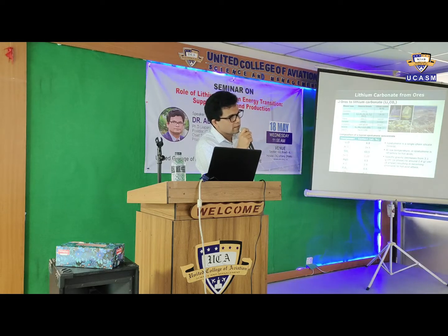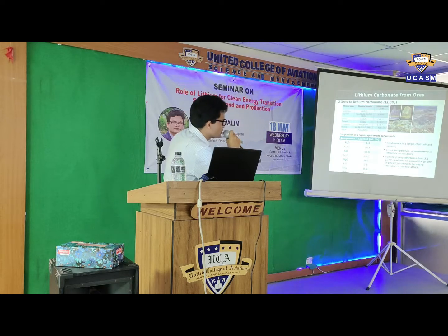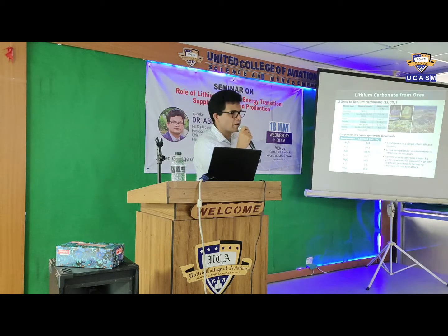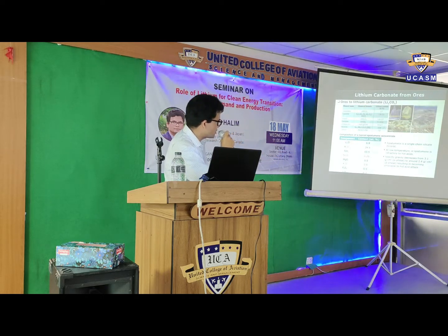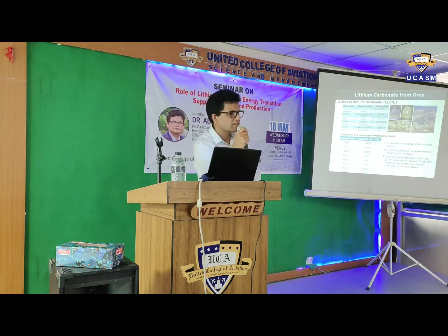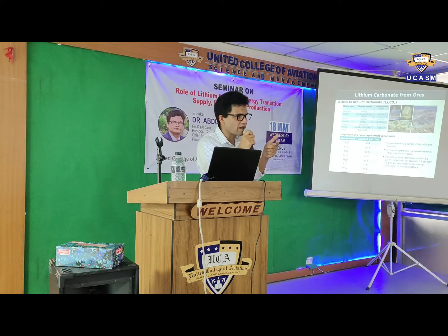Because of that, the mineralogical formation, the metallic rearrangement, and the density of this mineral. The specific gravity of this mineral is 3.1 gram per cubic centimeter. It means it's very dense. It's not easy to extract because it is, in chemical engineering terms, refractory to the acid. Acid does not easily attack this mineral as the density is very high.